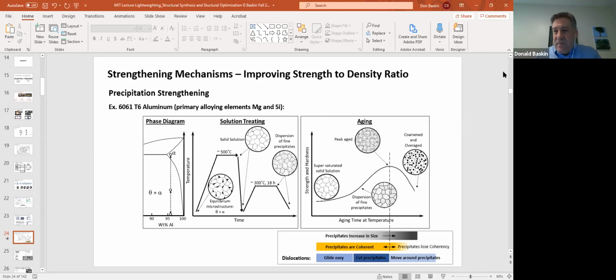The way that this is done is that the alloy elements are mixed up, and then the material is heated up to what they call solution temperature, which makes it thermodynamically stable for all those alloy elements to form a solid solution, to dissolve into the aluminum matrix. You quench this material, and then you start getting these little precipitates, sometimes only a couple nanometers wide, that begin to grow out of the aluminum matrix. And this will happen naturally. If you take a solution treated and quenched 6061 aluminum, quench it on Monday, put it on the side of the room, and wait till Friday, on Friday you'll find that it's stronger.